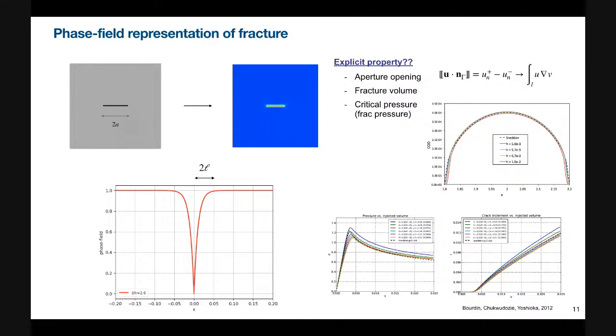So if we were to use a discrete approach to represent the fracture, fracture aperture would be the order of the size of the element that we have to use. But using this diffused approach, we can get away with much coarser, much bigger elements, even two orders of magnitude bigger. We are still able to represent this small fracture opening.